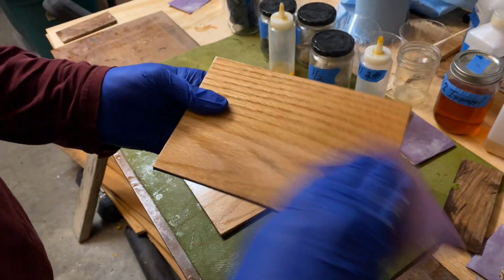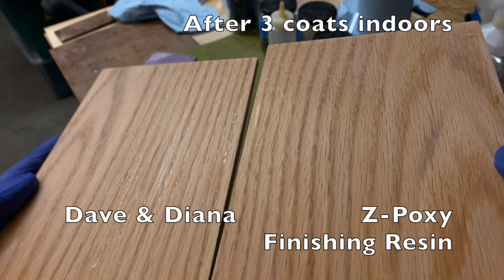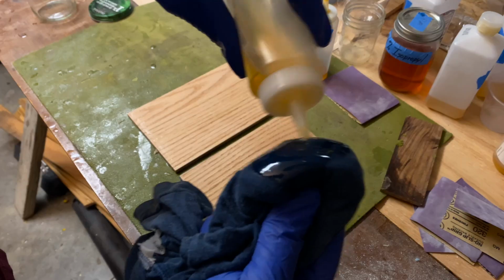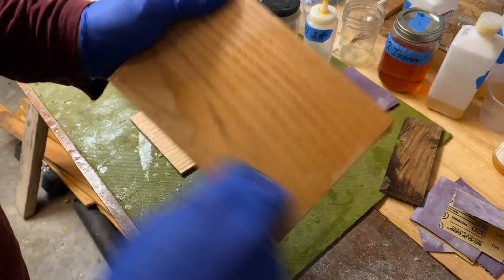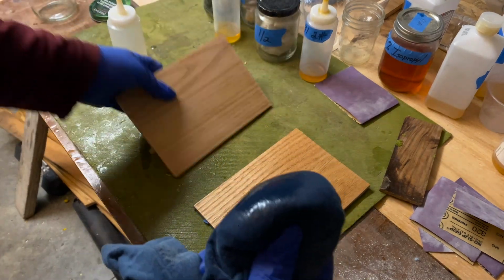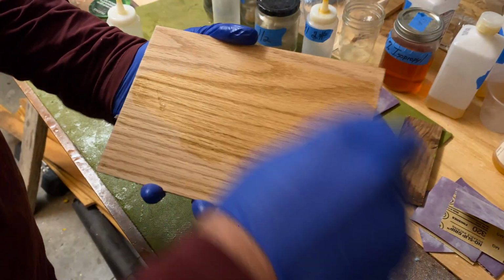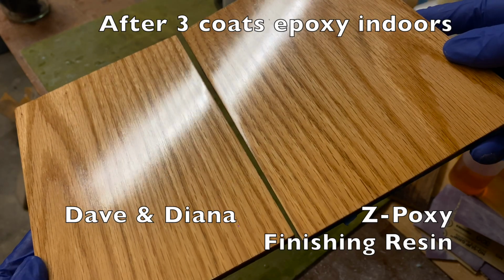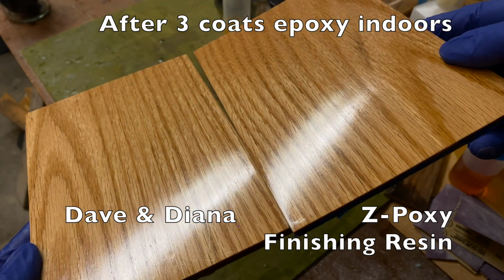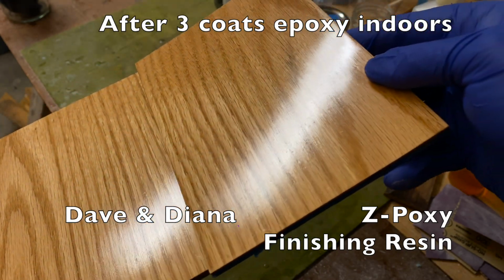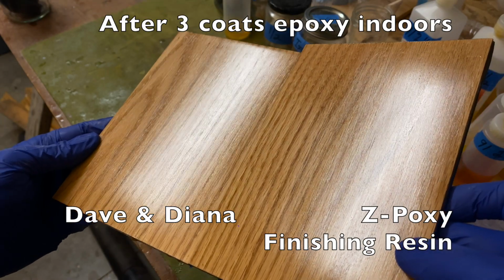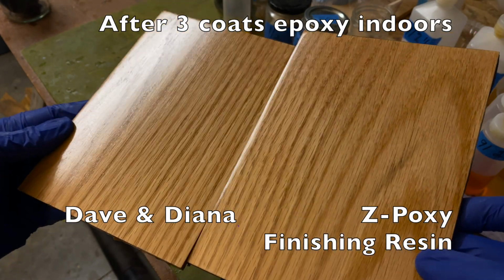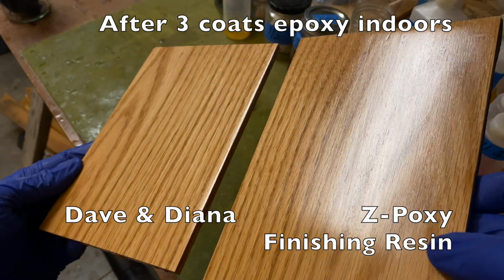I then sanded everything down to 320 again, applied shellac to the entire surface of the boards the same way we did before, and it seems like the third coat of epoxy on these boards was able to fill the grain. So purely in terms of grain filling, all of these epoxies prove to be comparable with getting the job done.